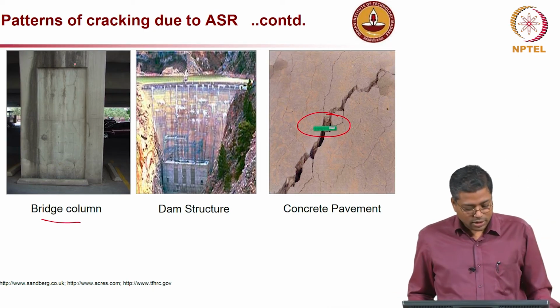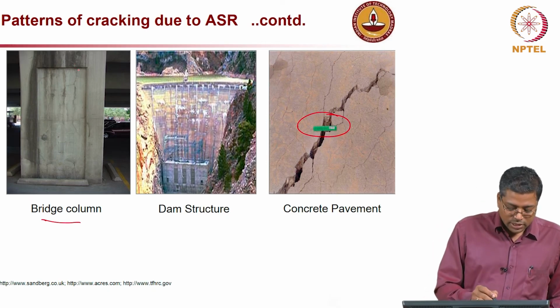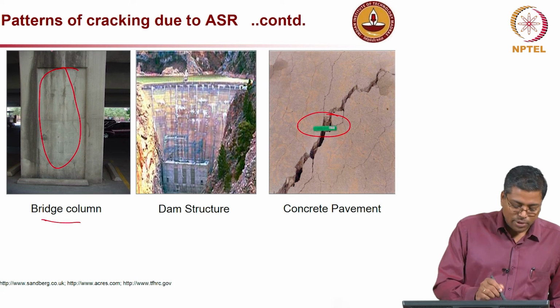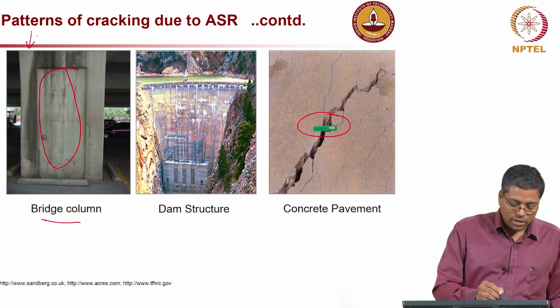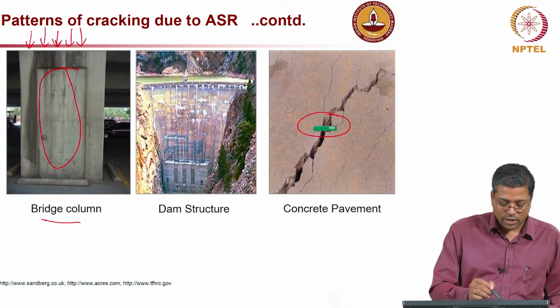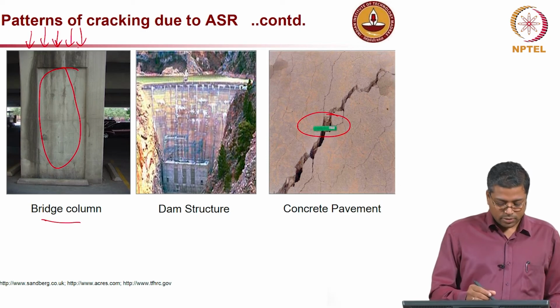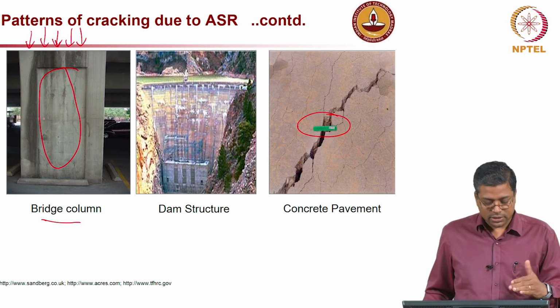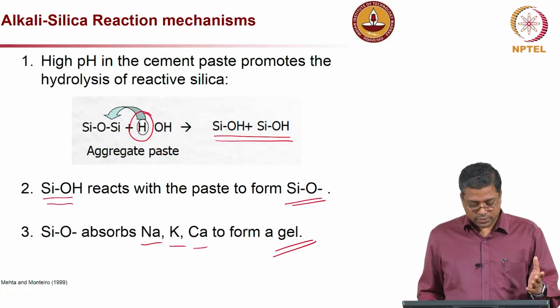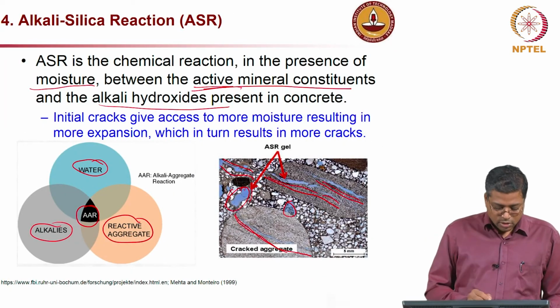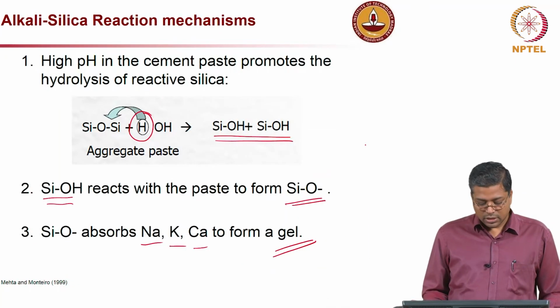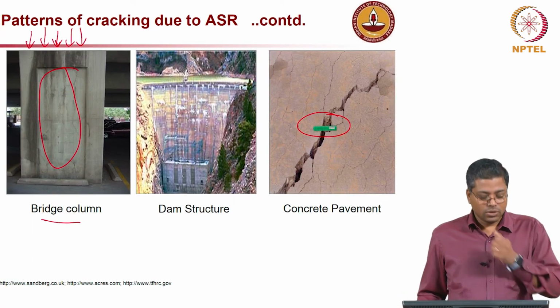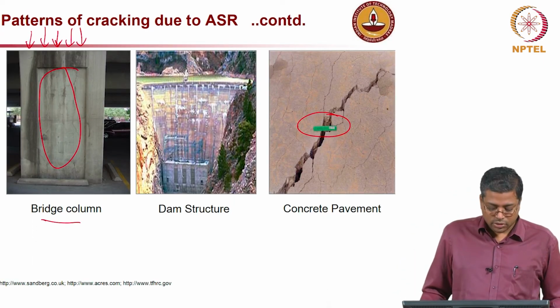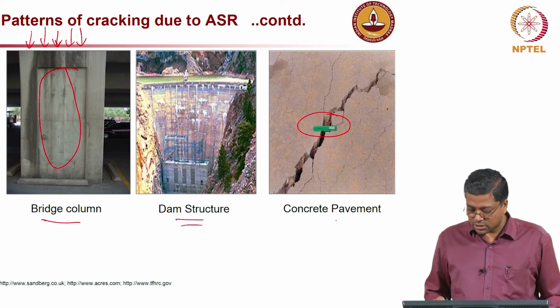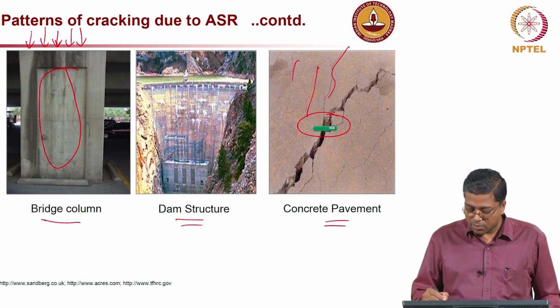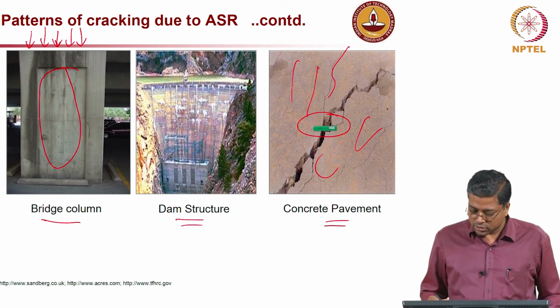Unfortunately, I do not have a photograph of the other side, but you can see here there is significant cracking, and this is mainly because there was a drain pipe providing sufficient moisture for the ASR reactions to happen. As I showed earlier in the bottom left picture, water is also a key factor. So, if you can keep the structure very dry, you may not see ASR induced reactions. There are other examples, like a dam structure and concrete pavement, where you can also see significant map cracking. These are all due to ASR induced cracking.